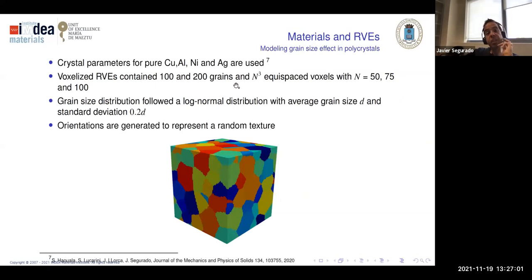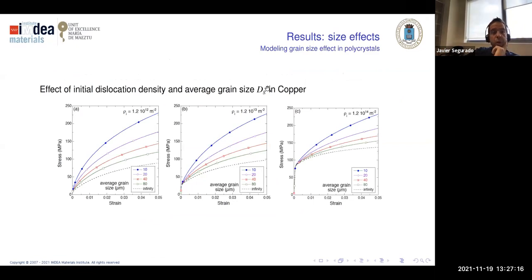So we use different materials, copper, aluminum, nickel, and silver, all FCCs, with different grain sizes and RVEs of this type. First we check in the model the effect of the initial dislocation density, with no GNDs, just purely statistically stored dislocations. We see that the model predicts a dependency of the yield on the density of dislocations, which is correct. The second thing we see is that with different grain sizes, we get the type of effect we see in Hall-Petch, that is, the smaller the grain, the harder or stronger the material. Here we are combining two items, not like in Hall-Petch, because in our model we can plug in the initial dislocation density in addition to the grain size.